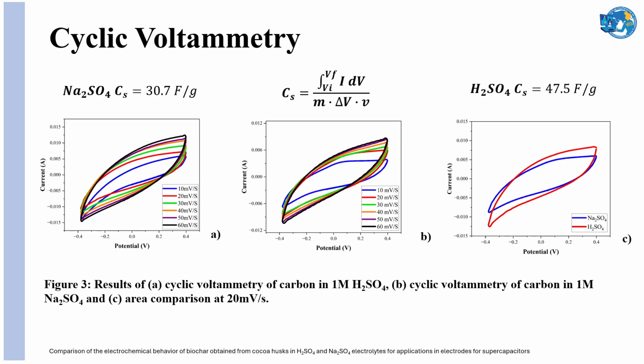The behavior of the material obtained in cyclic voltammetry is observed here. These analyses were carried out at different speeds, 60, 50, 40, 30, 20, and 10 millivolts per second, in two different electrolytes, sulfuric acid and sodium sulfate. In both cases, the change in the area of the quasi-rectangle can be observed as the scanning rates decrease. This affects the specific capacitance obtained because the ions have more time to interact with the working electrode as the scan rate decreases.